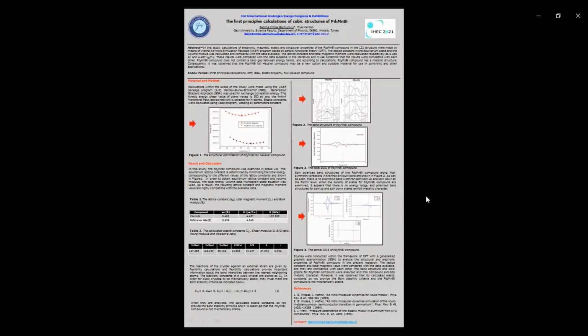As a result, studies were conducted within the framework of DFT with the generalized gradient approximation to analyze the structural and electronic properties of the Pd2MnBi compound in the present research. The lattice constants and total magnetic moment were compared with the available data, and they are compatible with each other. The band structure and DOS graphs were analyzed, and this compound exhibits metallic character. Moreover, its calculated elastic constants do not provide the stability criteria, and the compound Pd2MnBi is not mechanically stable.